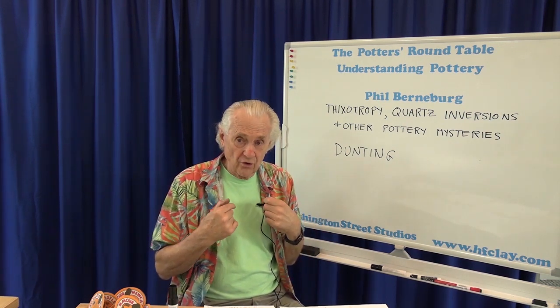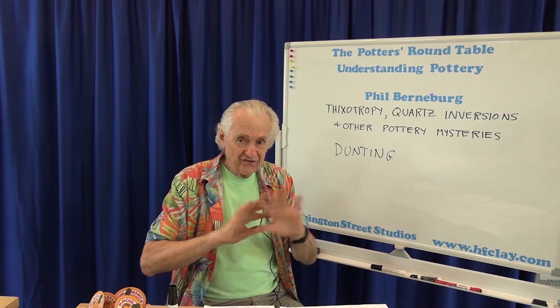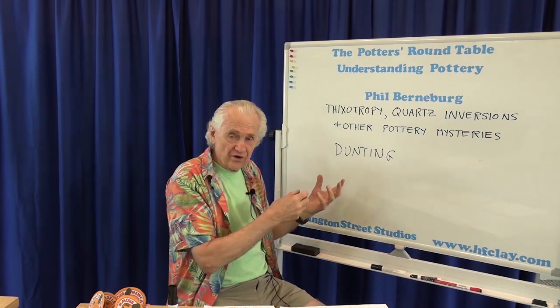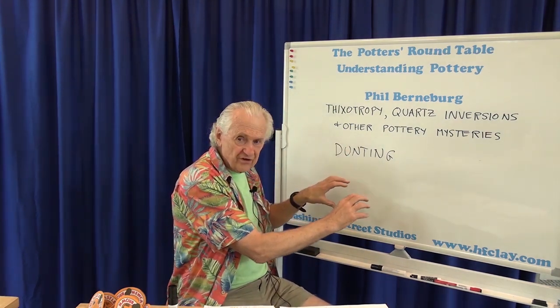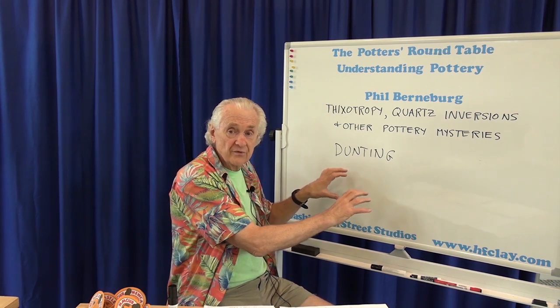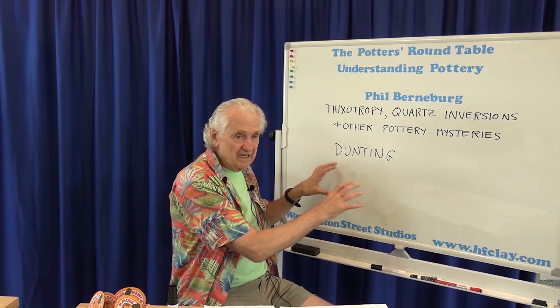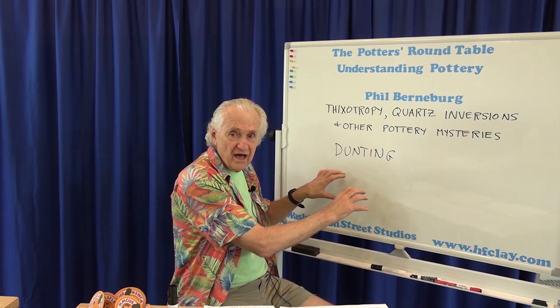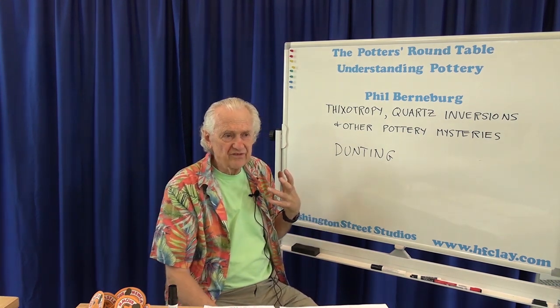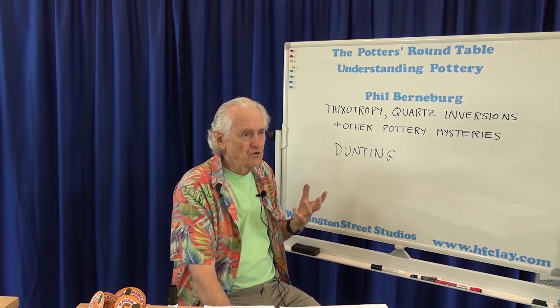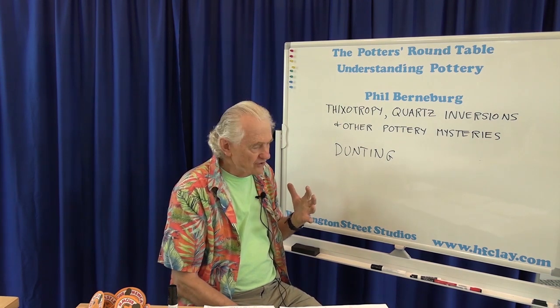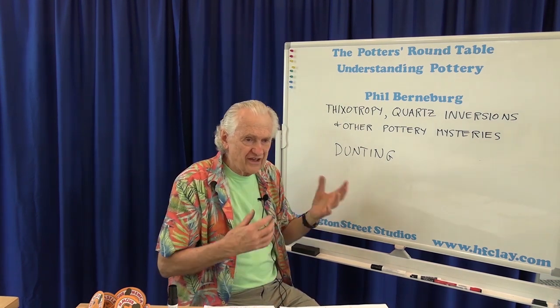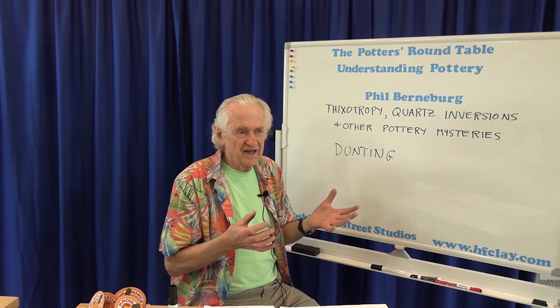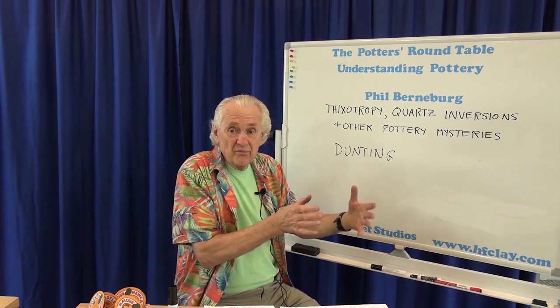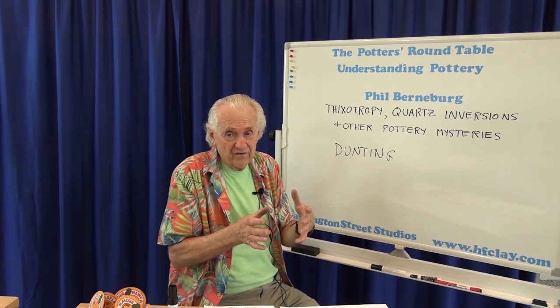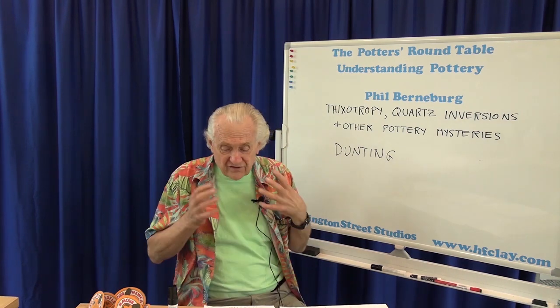But if you're refiring work that has gotten completely dense, that's a whole different situation, because now if there's a lot of little quartz particles in it and they want to expand, there's no room for them to expand. So in that case, I can believe that, yes, it could crack the pot. I don't know whether this idea that heating it up too quickly can cause cracking because of the quartz inversion is accurate. I'm just guessing that maybe it originated from the fact that people were refiring pots in the same firing as bisqueware. I don't know, but I've just never seen that effect.